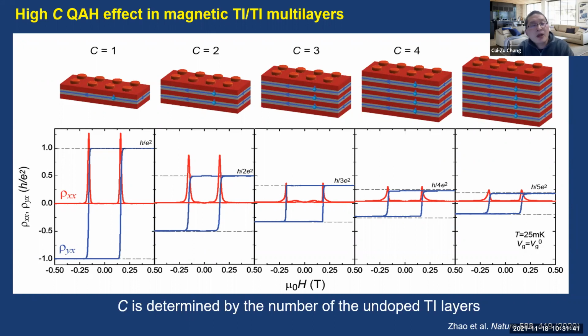Compared to the natural Weyl semimetal, here there is only a pair of Weyl nodes. And these Weyl nodes can be tuned by the magnetization in the film. When you change the magnetization, the Weyl nodes will sweep towards each other. Now, as you said, since we published this paper, my student further optimized the growth condition. Now I can tell you the maximum Chern number in my group we could grow is C equal to 10. When C equals 10, the Hall resistance is quite small, just 2.5 kiloohm. It's very difficult to distinguish whether this is C equal to 10 or C equal to 11 or C equal to 9.